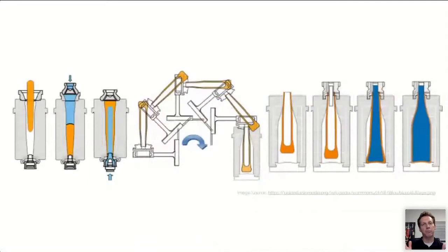If we look at the glass bottle mold manufacturing process, the glass bottle manufacturing process generally, typically you use two molds. On the left, you see a pre-mold and then a final mold. Okay, the glass, which is orange, comes in, air blows its initial shape, which ends up being the top of the bottle. It gets flipped over, and then air is blown in a second time, which forms the rest of the bottle. And in practice, it looks something like this.